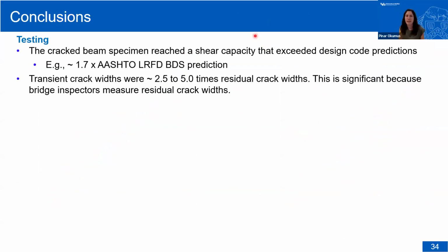Okay, so the conclusions from our entire study. First I'll make the conclusions on what we learned from testing. We learned that even though your beam may be cracked in the field, really the design codes will likely still give you conservative predictions for the capacity. For example, for AASHTO, what we measured was 1.7 times what AASHTO predicted as the capacity, even when we cracked the beam first and then loaded it to its capacity. We observed that the transient crack widths, so the widths under the loading, are 2.5 to 5 times the residual crack widths. And that's significant again because bridge inspectors will be measuring residual crack widths, versus all the test data in the literature are on transient crack widths.